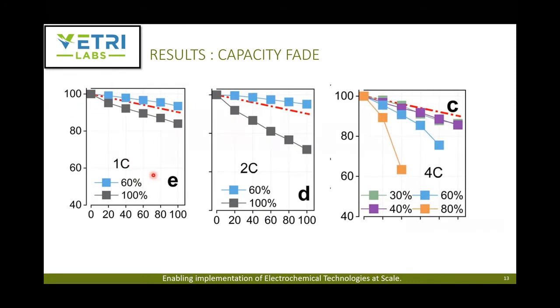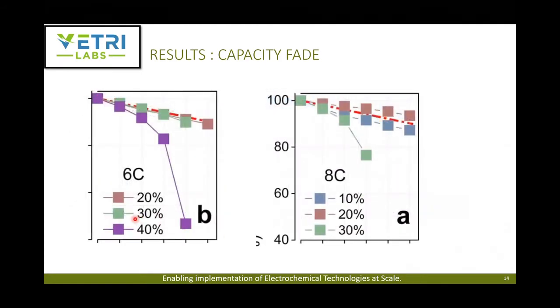So at 1 C, everything looks good, 60% SOC or 100% SOC, it's fairly linear. And at 2C, again, fairly linear, although at a higher slope. But as you go to 4C, at high SOC, you start seeing this nonlinear behavior. This nonlinear behavior is what they attributed to cascading failure or the rollover failure, where when you're looking at this linear region, you cannot predict the life here. So for example, at the 20 cycle cutoff, you cannot differentiate between these here. At least here you can differentiate at the 80% SOC. So it becomes nonlinear. It gets even more nonlinear, as you can expect, when you go to 6C and 8C.